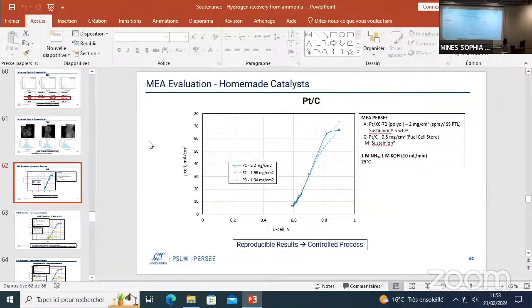But because, as I said, when I produced these kind of graphs, I really had a problem in the spraying, so I was doing several tests. I was solving the problem of the spraying as I was doing the tests. So most of the time I didn't have really the same catalyst loading, and I wanted to normalize the results to the catalyst loading. So I had to divide ampere per centimeter square by the amount of the catalyst to normalize. Okay. Because typically, the way I've seen kinetic data presented, it's directly the amps per milligram.